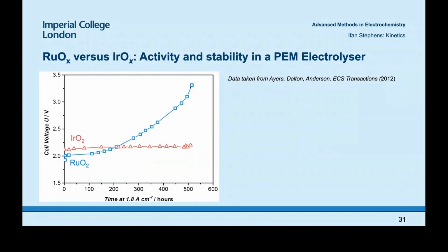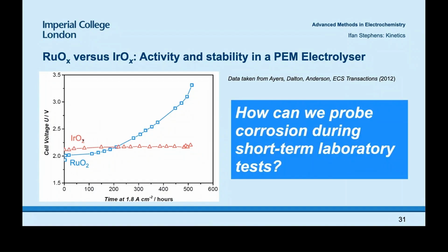The reason for this is essentially that under conditions where these oxides catalyze oxygen evolution, you have very, very positive potentials. In addition to getting oxygen evolution taking place, you start to oxidize the ruthenium or the iridium. So you have a side reaction of iridium or ruthenium dissolution. Especially in the case of ruthenium, you tend to make ruthenium cations at the same time as evolving oxygen.